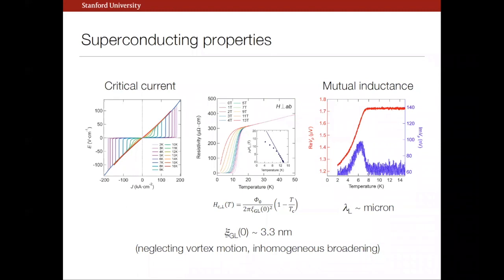If we look at the magnetoresistance of this transition, you can take off an estimate of the superconducting coherence length. We get something like 3 to 4 nanometers typically. And this is just neglecting details of broadening. This is kind of a ballpark number. And finally, with a dual coil mutual inductance measurement, you can see the superconducting transition and associated tuning. And again, at this early stage, it's very difficult to say quantitative things, but let's say, given a range of possibilities for the order parameter symmetry or the scale of effective disorder, in any case, we would get a few microns. So that's kind of the scale of the London penetration depth. So extreme type 2 in that regard.